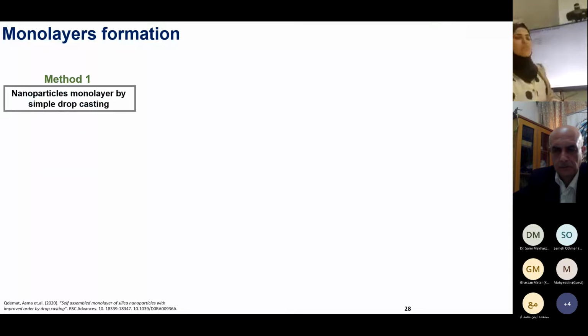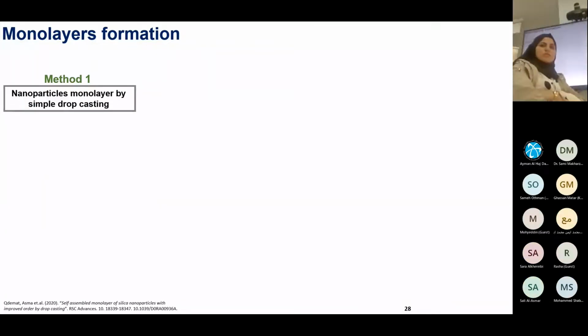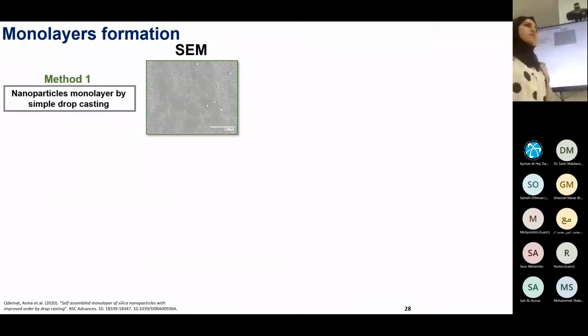So now I use this nanoparticle to produce the monolayer. To my knowledge, I was the first one who could obtain such a large, homogeneous, uniform monolayer over a 1 × 1 centimeter square silicon wafer. To produce this monolayer, I use three preparation methods. The first method is only self-assembly by drop casting, and I was only controlling the volume of the droplet.